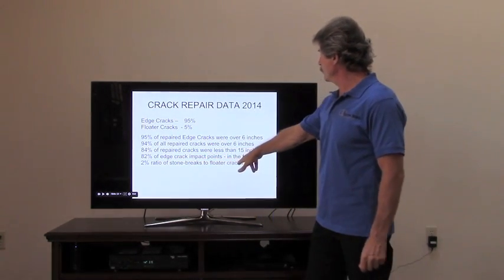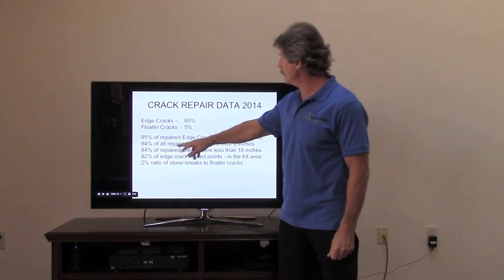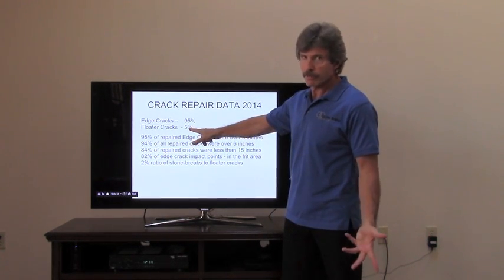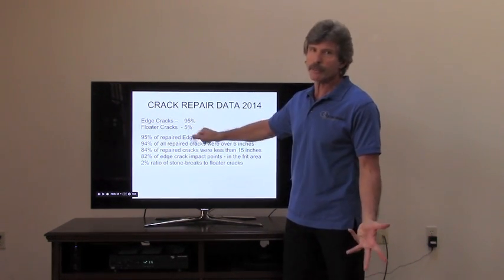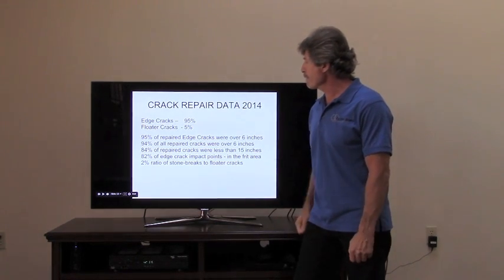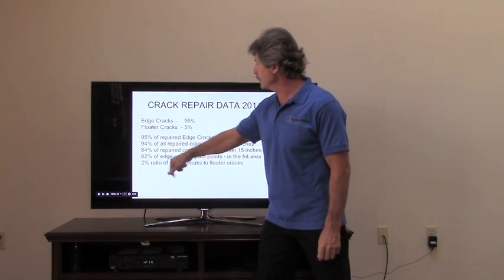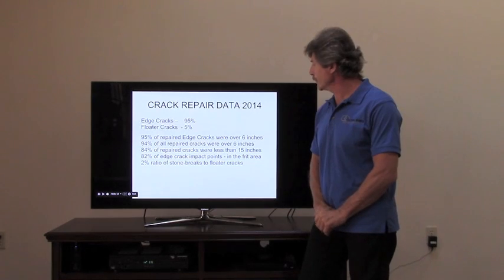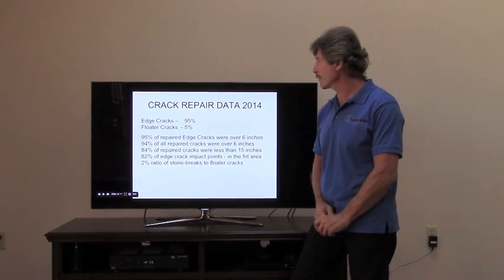The ratio of stone breaks to floater cracks. Okay, like I saw, floater crack. You'll like the fact that you don't see these very often because they're harder to fix than the edge crack. But our data showed only 2% of the actual stone breaks we fixed were actually turned into floater cracks.